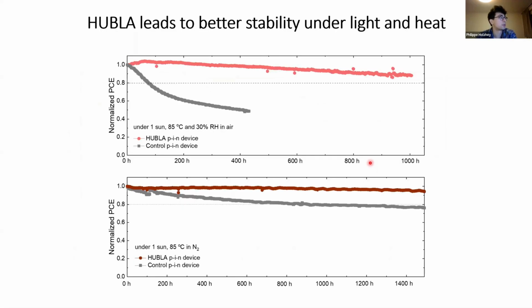And yeah, we also get some good stability. So this is encapsulated, but stored in air in the HUBLA devices. Quite stable for 1,000 hours, while the control very quickly degrades at the beginning. And in nitrogen measured at 85 degrees under 1 sun, we also see similar stability for over 1,400 hours.